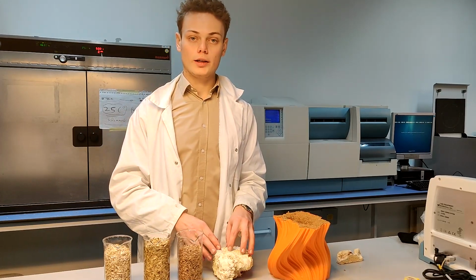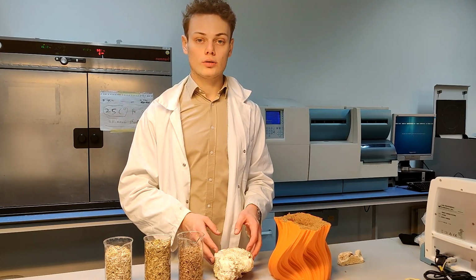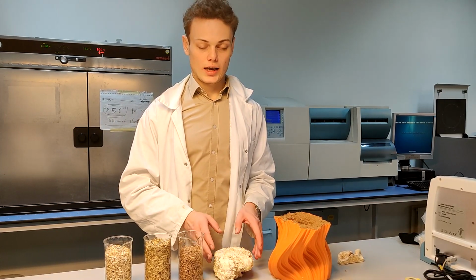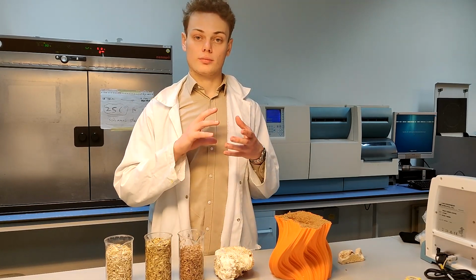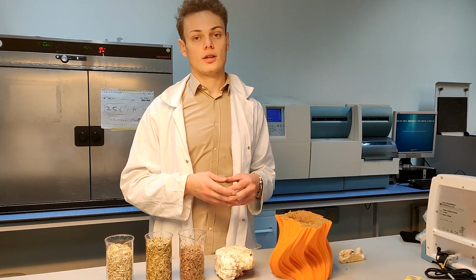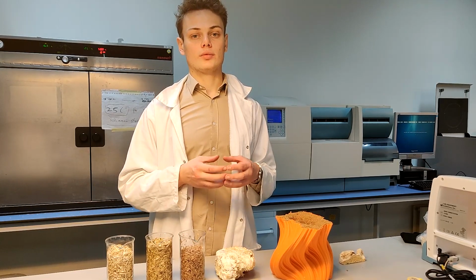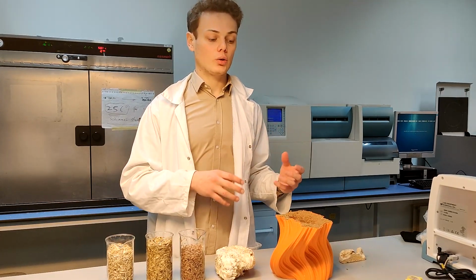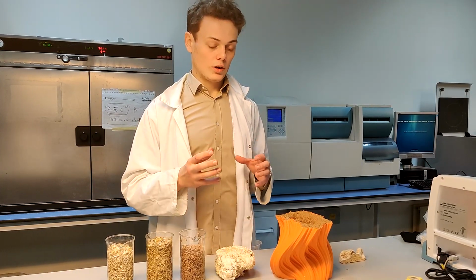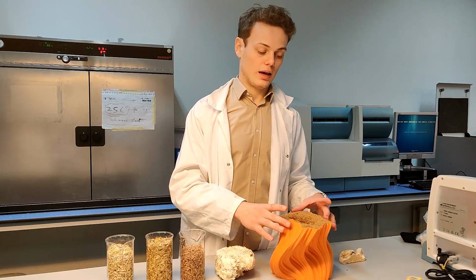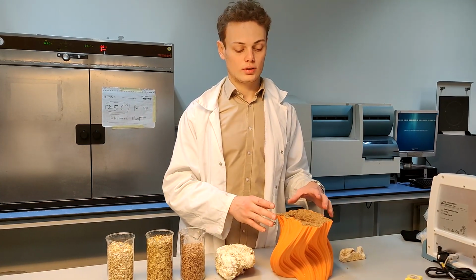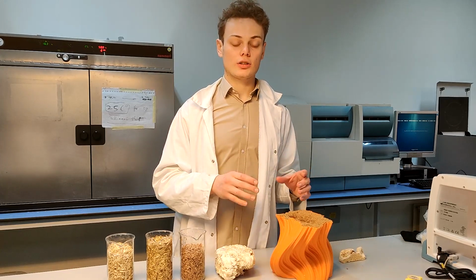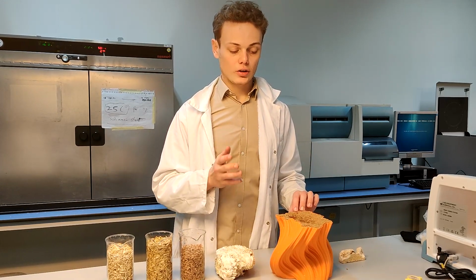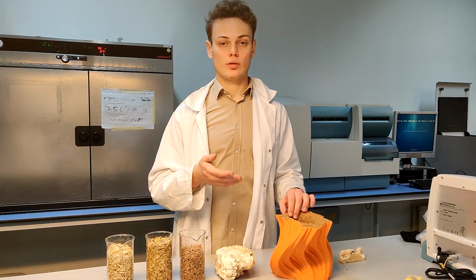After about 2 to 3 weeks, the mycelium has fully grown into the hemp fibers. At this point, the hemp fibers are broken up and shredded. Shredding the material allows it to have a greater detail in the final product. Once it's been shredded, we put the hemp fibers into the mold. After about 2 to 3 weeks, the new hemp material has fully taken over the shape of the mold.